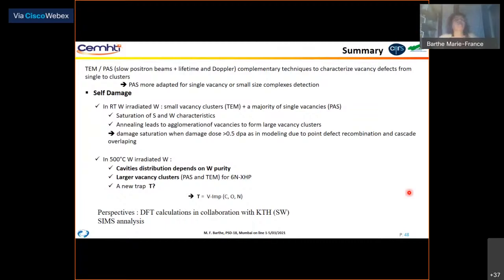So I will just summarize my talk, saying that, of course, TEM and PAS are complementary techniques to characterize vacancy defects from single to clusters, with a more adapted technique for single and small size complexes detection for positrons. We have seen that self-damage is created in tungsten with small vacancy clusters at room temperature, and the majority of single vacancies, which are only detected with PAS. We have seen that there is damage saturation when the damage dose increases above 0.5 dpa, as has been expected from modeling, due to point defect recombination and cascade overlapping.